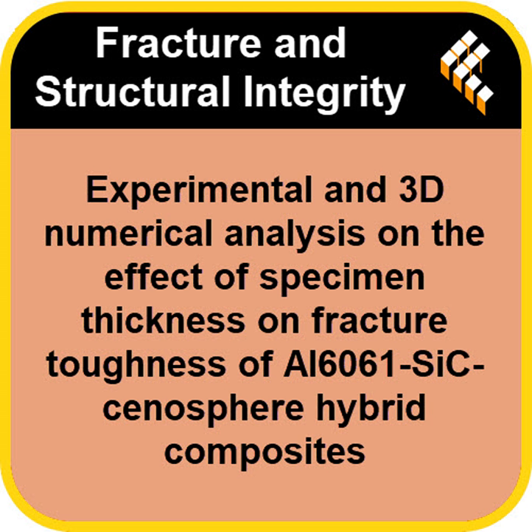Okay, the 6% wins. Let's dig into why that was the sweet spot. What did the fractured surfaces show under the microscope? Yeah, analyzing the fractography, the study of the fracture surfaces with FESEM, was key here. It showed the main failure mechanism, for all of them really, was particle debonding, the aluminum matrix pulling away from the reinforcement particles. Okay. But in the poorer performers, the reasons for that debonding were different. For the 3 wt% cenosphere composite, the one with the lowest toughness, there were just too few particles acting as barriers.